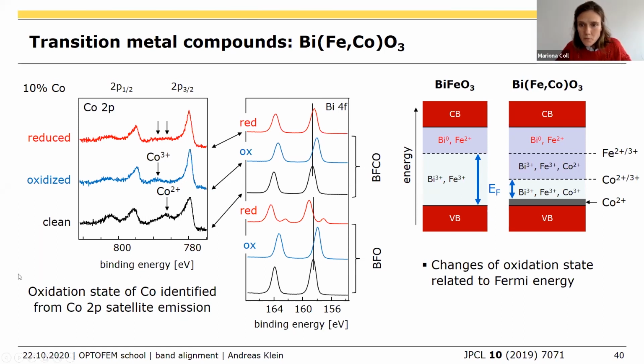Okay, so we have another question from Gael. Do you use other techniques besides XPS to measure energy levels? We measure some defect energy levels also with electrical measurements. Yes, we do. In principle, we obtain activation energies. This is very similar to semiconductors. You get the defect energy levels, which you can measure quite accurately with electrical measurements. But this is still in development, because all these defect levels, there are many of them in the band gap, and they are so important, they are barely known.